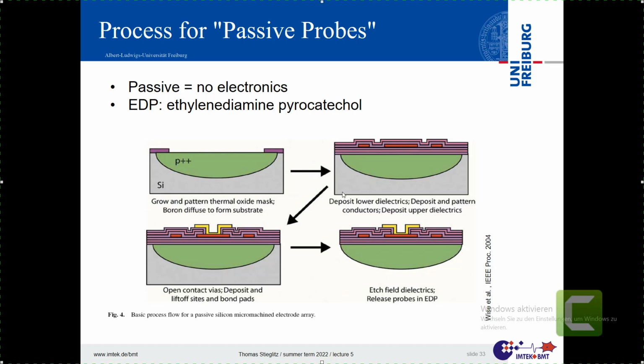And if we put that into EDP, and the long name is above there, EDP etches everything but highly positively doped silicon. That means that doping front forms a natural etch stop. So if we put it in, it does not etch silicon oxide and silicon nitride, so our insulation stacks here, and it does not etch gold or platinum or iridium oxide, just silicon. That means all silicon has gone away, and the rest is positively doped silicon and the insulation material.